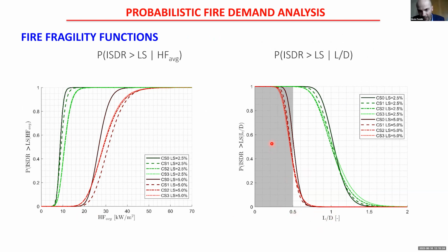Here you can see that this is the gray zone. It means that when L over D is smaller than 0.5, the column is in part engulfed in the fire. So in this case, this intensity measure would not be relevant for our analysis. This is the reason why this is the gray zone. And here are the fragility functions that are built for the 4 different case studies for the heat flux. What we observed, of course, is that when we consider the nominal characteristic value of the yield strength, the probability of the interstory drift ratio overcoming our limit state is higher, because of course we use a characteristic value, so it is 5% per time.